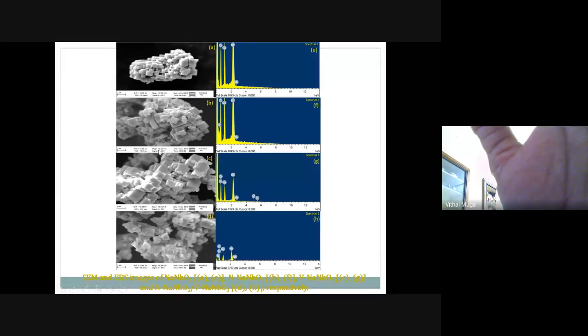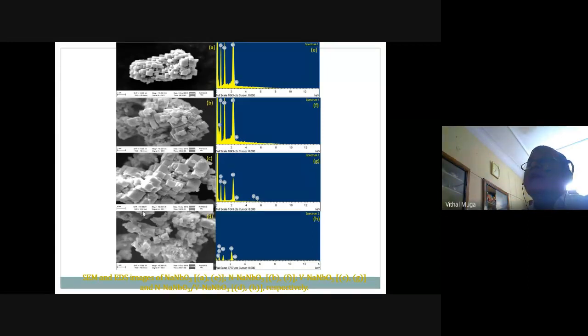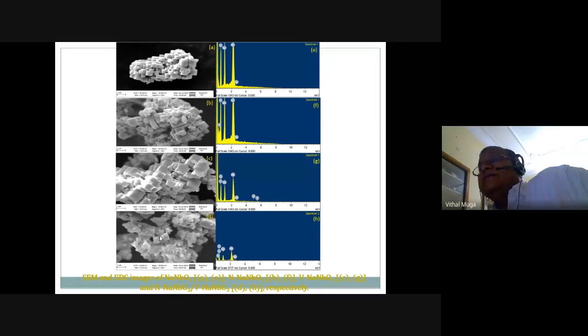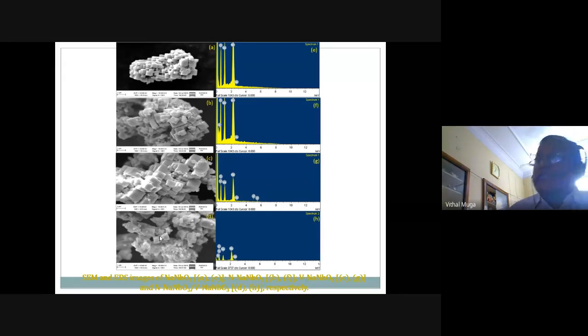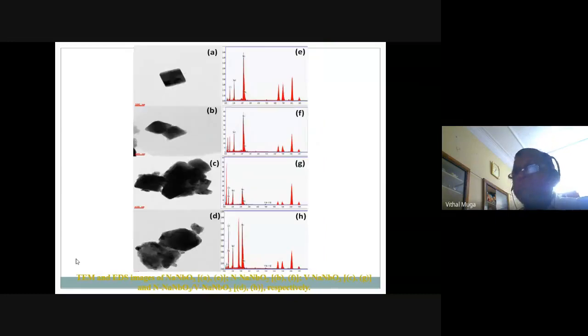This is simply because this material and this material are physically mixed and ground thoroughly. When you grind it, the edges will go away. Edges will be broken because of the force we apply with the mortar and pestle. That is why the edges in this have disappeared. Now this is one important point we answered for the reviewer's question. This is a classical observation that it's a physical mixture of two important materials.